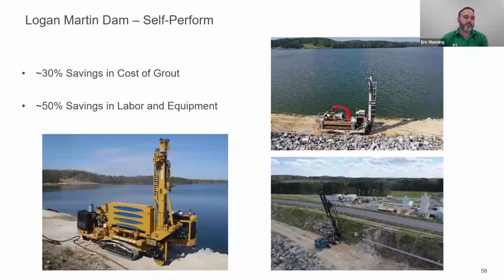So in addition to the 30% volume savings that we've gotten from this new composite hanging grout curtain concept, we've recently begun a low mobility grout mix development program where we're trying to get away from fly ash, because now fly ash is in low demand with fossil plants closing down one by one. And so in an effort to get away from fly ash altogether and get away from our dependency on it, to keep our grout cost effective, we began removing the fly ash out of the mix and substituting local clay, borrow material from here on site.